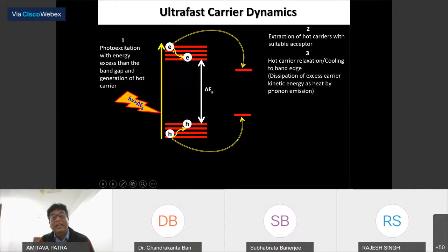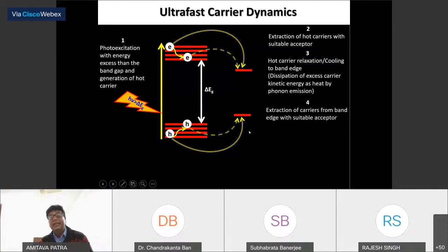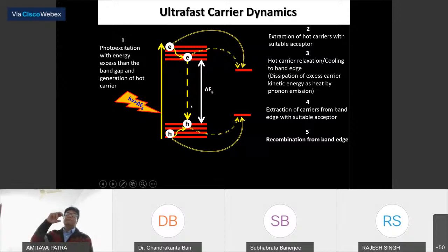But the second step is that it can relax before extracting, it can relax over here. That is the hot carrier cooling to the band edge, or from the hole. Or the third process is that you can take the electron from here to here, extraction of the carrier from the band edge. That is called the cold electron, and that is called the hot electron. So all these processes take place, and this recombination process takes place in the nanosecond time scale. This extraction takes place in the femtosecond time scale. This takes place in the picosecond or femtosecond time scale.